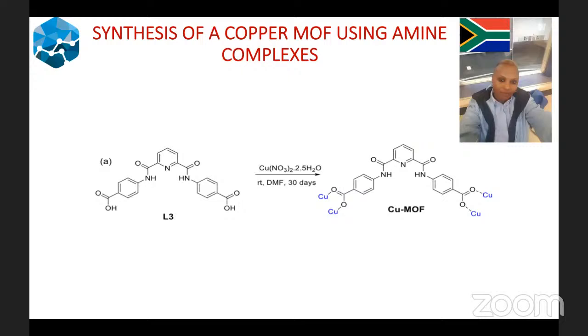Dr. Mehlana, since we have these complexes with carboxylic acid as the coordinating site to the metal in MOFs, do you think adding some protons will activate the reaction? Addition of protons instead of base will create a weakening of the coordination of the ligand to the metals, and then we have a better number of vacant sites. So the open sites of the metals will increase because of the weakened coordination of the carboxylate on the metals of the MOF. Then one of the linkers will be weakened or dissociate to create open sites, which is probably one of the reasons for the increase. Are there any experiments on this?